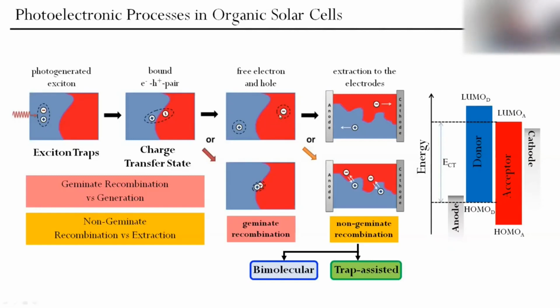So then in ideal world, they would be just transported through these networks of donor and acceptor material and collected by anode and cathode. However, in real life, there are problems. First problem, called geminate recombination, is recombination of charge carriers from the same exciton. So instead of being separated completely, they can come back and recombine at interface. So it means that we lose this photogenerated exciton, and we don't want to do this because this causes loss of our photocurrent.